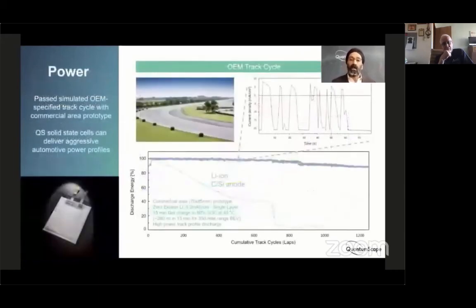You can put all of those things together and test these single layer cells on the most aggressive type of driving that you can put a battery through, and that is a track cycle. So in this case, one of our OEMs has a racetrack on which they test their cars. The drive cycle for that racetrack is essentially oscillating between one extreme or the other. So you're either discharging the battery at full power, or you're recharging the battery when you brake around the turns at full regeneration power. And the battery just swings back and forth between two extremes, which again is the most stressful driving condition for a battery, because batteries hate to be driven this aggressively.